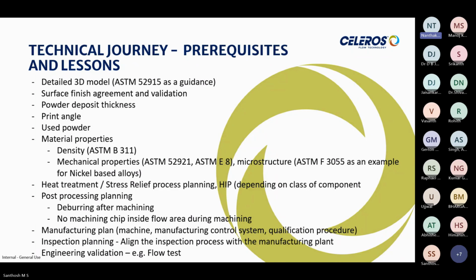Print angle: normally our components got printed at a 45-degree angle, and when we started, we didn't have any big challenges about it. But as we started asking for bigger parts, we found that the print angle was certainly a factor that was not allowing us to make bigger parts. So that's something that you'll have to discuss with your service provider, in this case Wipro 3D, and get their help so that they can find a different angle by making some changes, which is DFAM. And I think that will help us in making slightly bigger parts, better parts, quicker, with some better properties.